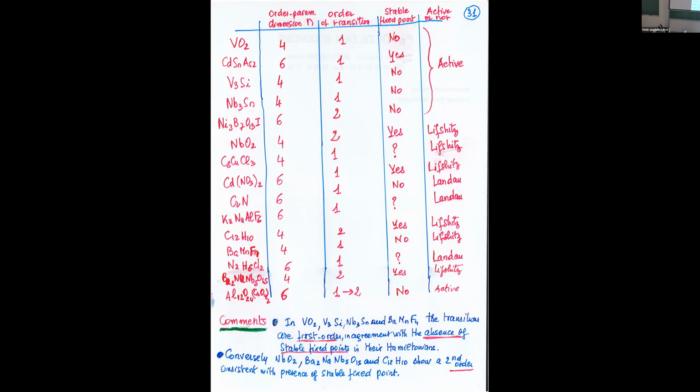So let me only summarize here. At the beginning, people tried to understand why, especially because the k, you remember yesterday I said that the Lifshitz condition selects a number of points in the Brillouin zone, the center and some high symmetry points on the surface, which fulfill this criterion. Okay? All right. But then people began to find that many times the wave vector was temperature dependent and began to move in the Brillouin zone. You can even find it at a completely irrational value. So they began to say, okay, here